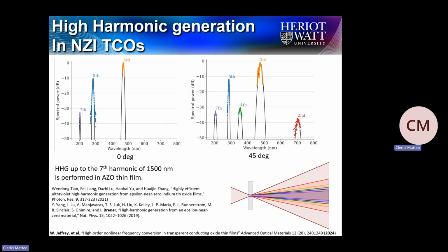Okay, so again, one thing that is useful for understanding these materials is that it is good to look at them as, let's say, a super metal, if you want. Fundamentally you have a metal where you have one order of magnitude higher chi3 and three orders of magnitude less losses. So it's a super metal. Of course, three orders of magnitude less losses than metal is still quite some losses, right? But still, for integrated photonic purposes, when you can propagate for a few microns, it is a lot, instead of having a penetration depth of 10 nanometers. So that's the fundamental difference.